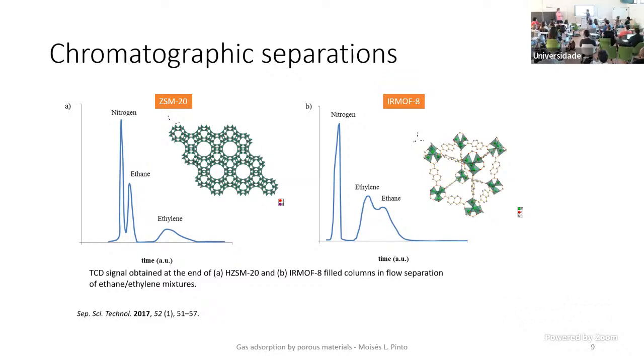Why? Because in this case, ethylene adsorbs much more to the surface of the material, so it takes more time to come out. But if you change the material, you can have another order at the output. So we inject everything again at the same time, and then you have nitrogen coming out first, then ethylene, and then ethane. So you see, we switch the selectivity of these two hydrocarbons because, of course, the material is different. I'm not going to try to explain why this happens. This is just to highlight that we can also perform adsorption experiments in many different ways, also to understand the possible applicability of the materials.